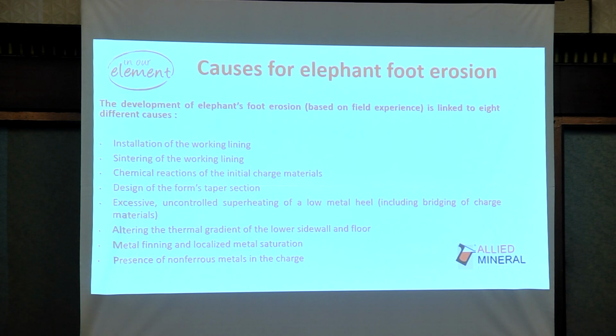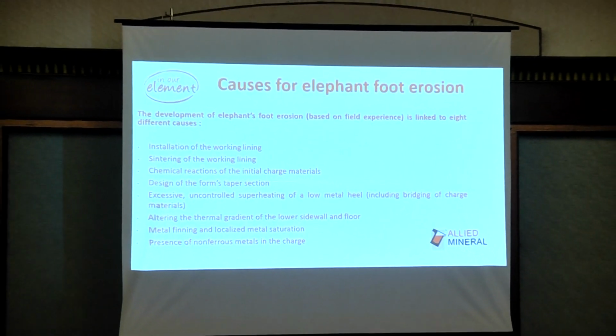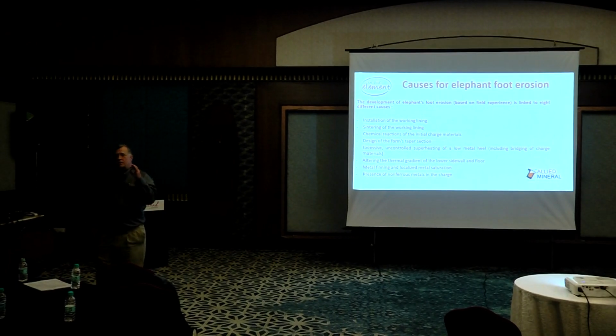Installation of the working lining can cause it. That means you get saturation, that actually lowers the melt point of the silica and can lead to rapid erosion. Sintering, again, those two come together. If it's improper sintering, you're going to get either penetration and superheating or saturation and melting of the lining. Chemical reactions of the initial charge materials. Okay, the charging process is most critical for elephant foot erosion.